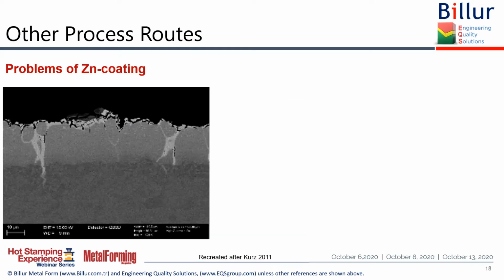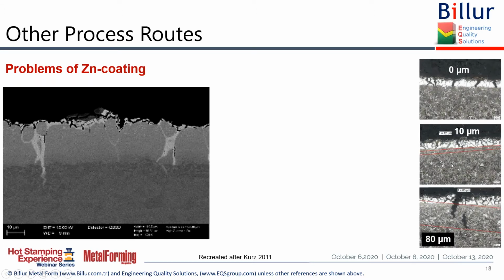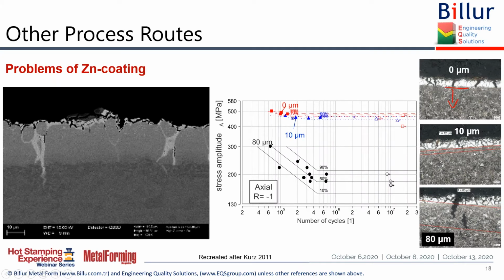As I said, the problem with zinc coating is if there's liquid zinc, it can go inside the base metal. And there has been a number of studies. What would be the problem? How many microns of the crack going inside the base metal would create problem? And it looks like if you have a micro crack that goes only 10 microns deep, like this one, it's not really changing your fatigue life significantly.